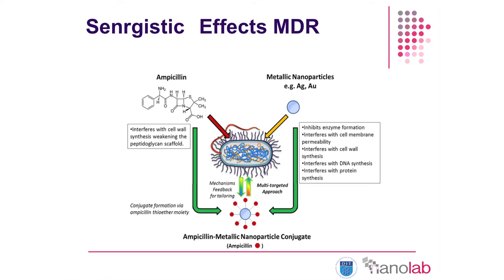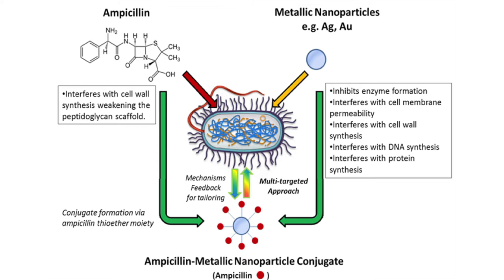Some of you may be familiar with antibiotics running out — penicillin is coming towards the end of its lifespan because so many bacteria have become resistant to it. We have multi-drug resistant bacteria like MRSA and C. diff. What we're trying to do in DIT is combine the antibiotic effects of penicillin with our nanomaterials to get more bang for our buck — trying to kill bacteria in more than one way. If we don't kill it with the silver, hopefully we've weakened it enough that the antibiotic can do its job, via covalent bond with the thiol moiety on the ampicillin.